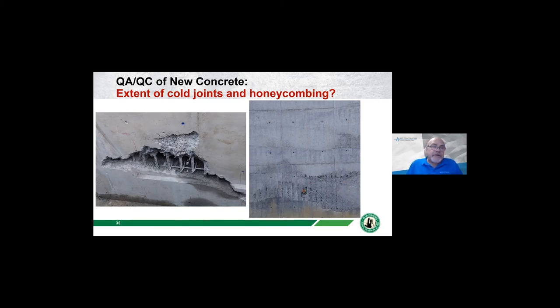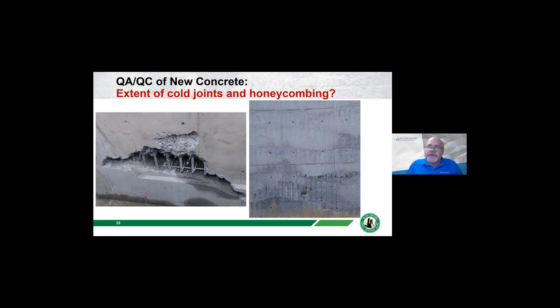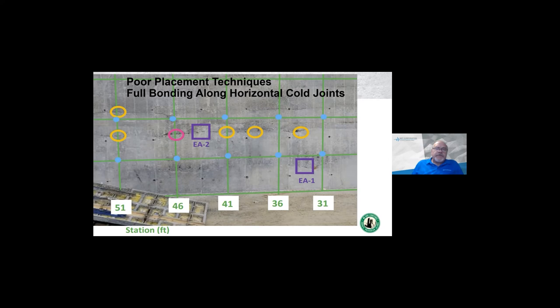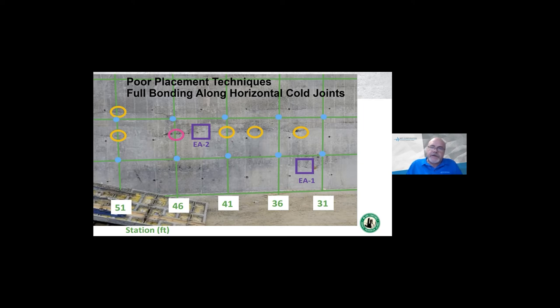This is often done on new concrete when consolidation issues are present—the concrete just wasn't vibrated properly. We want to understand the extent of honeycombing or a cold joint, say if we were waiting for a concrete truck in the middle of summer, to make sure the top concrete pour is well bonded to the lower section. We lay out a grid system and put our sensors over that visible cold joint. If we get a signal between sensors two and three, the upper concrete is well bonded to the lower concrete. If we don't get a signal, the lower section started to set up and the top section is not well bonded.